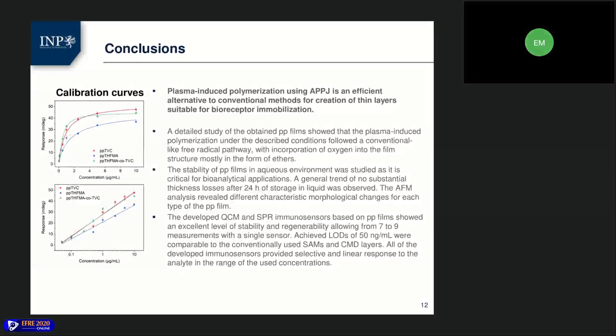The constructed calibration curves showed a good linearity in all of the cases, but the best agreement with the linear fit was achieved for the copolymer-based sensor. So, to the conclusions. Plasma-induced polymerization using an atmospheric pressure plasma jet is an efficient alternative to conventional methods for creation of thin layers suitable for bioreceptor immobilization.